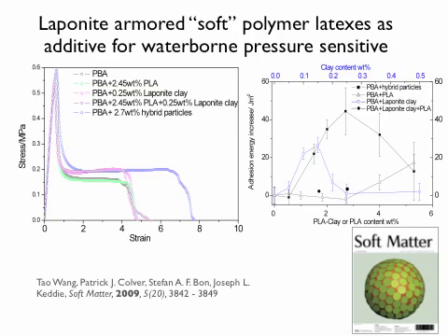So what did we do? We basically made these armored particles, butyl acrylate, polybutyl acrylate, which is a bit like chewing gum, right? It's really soft. The side chains can crystallize a little bit potentially at 0 degrees, but the Tg is very low. So it's quite a gooey thing, armored with clay particles. And then one of the applications could be stickers, pressure-sensitive adhesives, which are a sticky material.